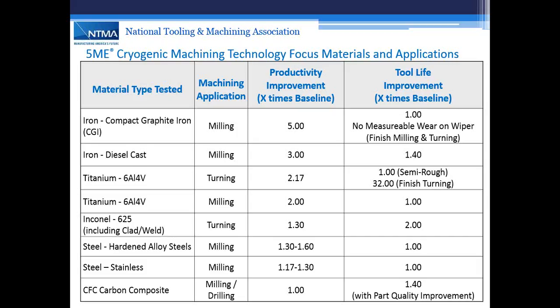Hardened steels, I think this was a 4340, 40 Rockwell material, 30 to 60% metal removal rate increase at equivalent tool life. Stainless steels, anywhere from 17 to 30% metal removal rate increases at equivalent tool life. Carbon composites, couldn't run any faster because the machines are already running max RPMs, but we saw 40% improvement in diamond vein tooling, which is extremely expensive, so there's a significant benefit even on carbon composite materials. Next slide.